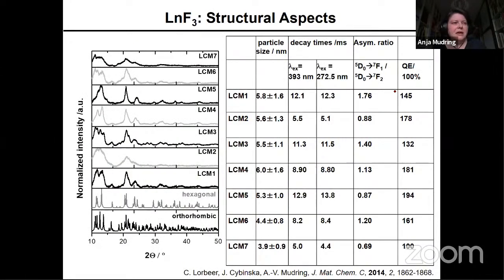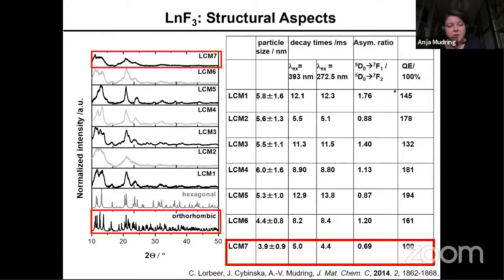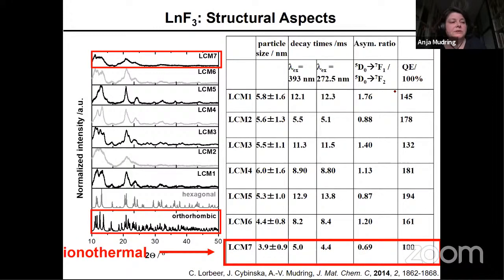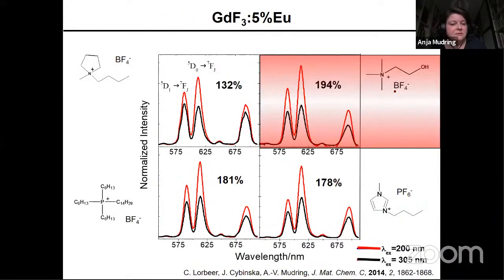So when we came home, we looked a little closer at the powder patterns to identify what kind of polymorph we got. And indeed, we found that the material that has the superior quantum yield almost exclusively featured the trigonal tysonite type, and then we made, by simply heating, the orthorhombic yttrium trifluoride material, and there you don't observe the effect at all. So that was something that people had not observed before, and that just showed the importance of the polymorph for the whole story. So we learned the lesson. We were really happy.